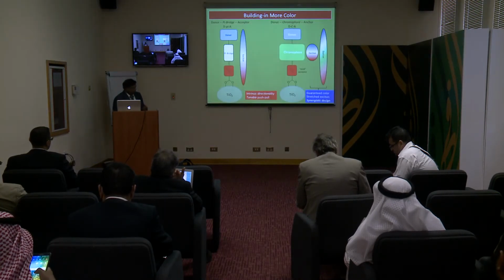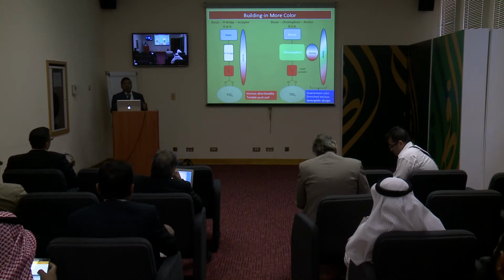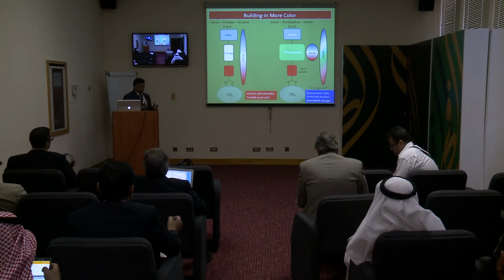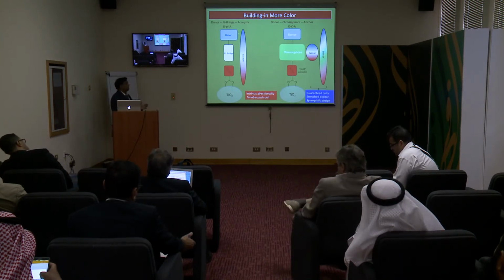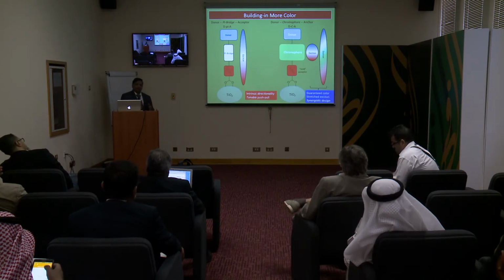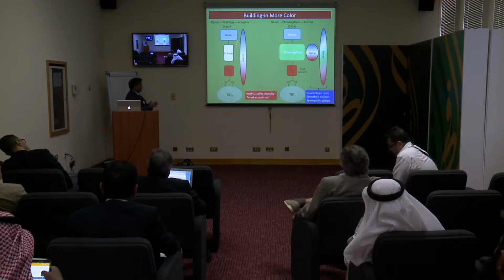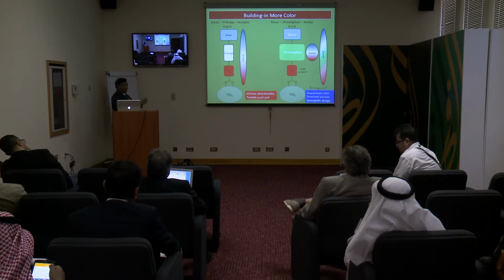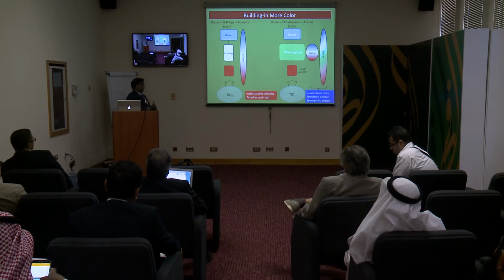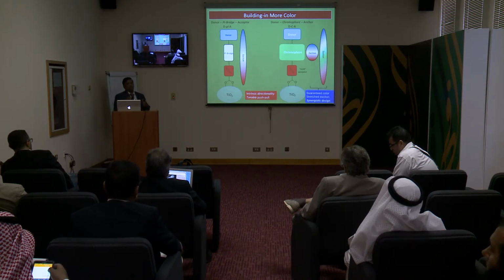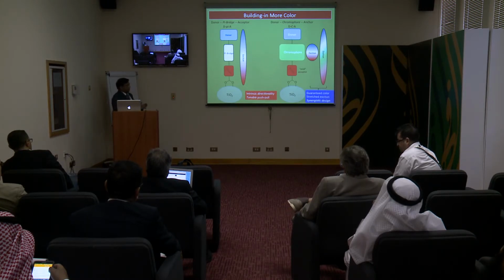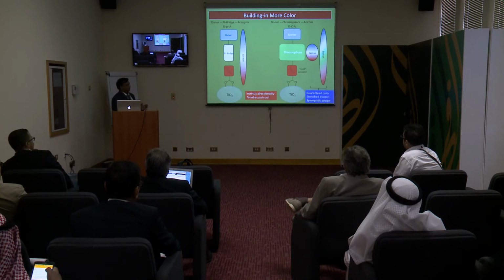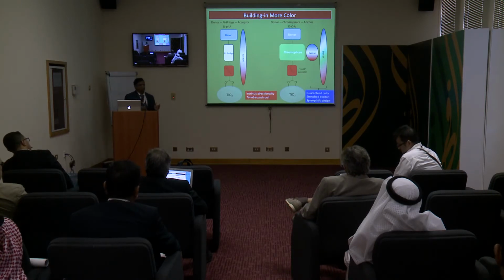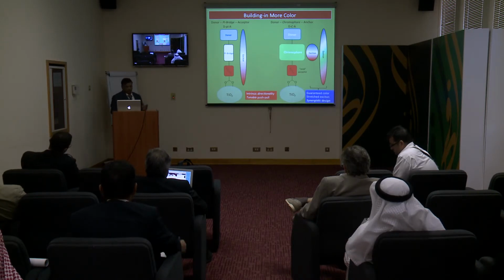So now I will move on to how one can tune the spectral properties of the organic dyes. The organic dyes are divided into mainly two categories. One is the D-pi-A dyes, that is donor, pi conjugation, acceptor, and the other one is a donor chromophore and an anchoring group. The difference between these two families is that here, by increasing the pi bridge, you will create the charge transfer transitions, and then you will get the color. Whereas in this family, we are selecting a chromophore, which is already a colored molecule, and then we are tuning further the spectral properties by substituting the donor with different donors, or with different anchoring groups or different spacers, to see how it will affect it. So I will go one by one here.